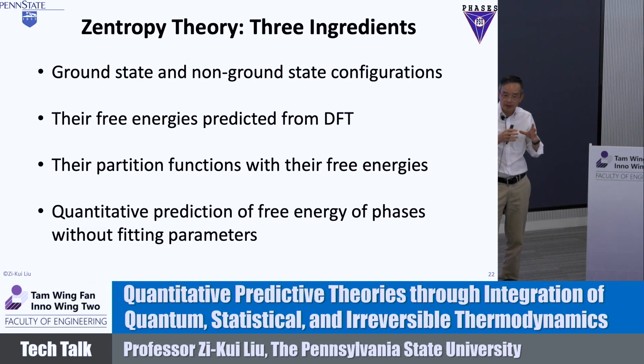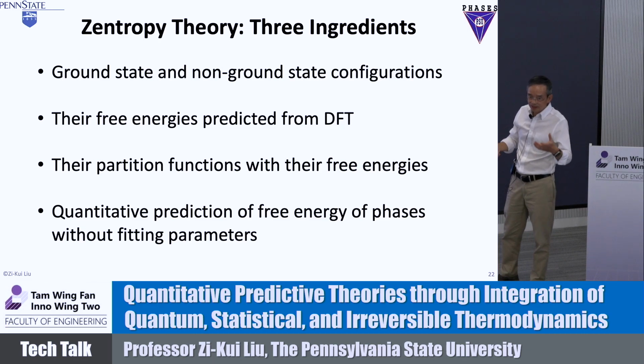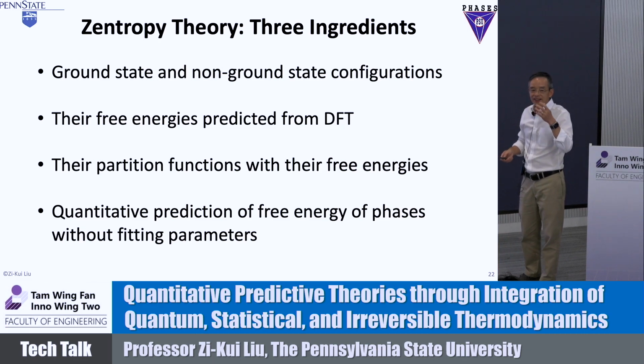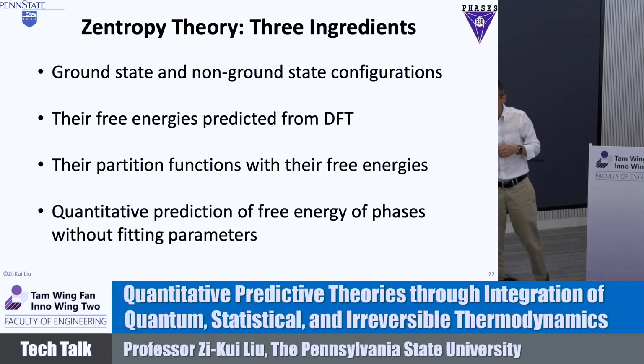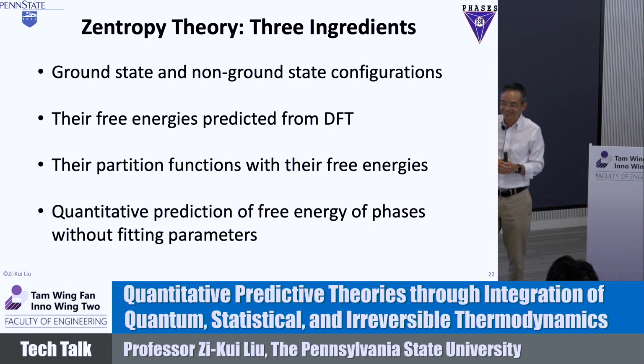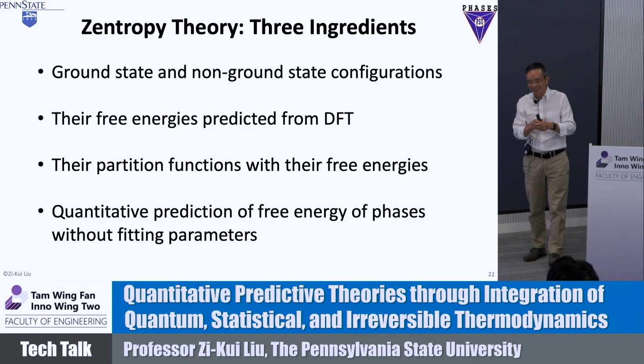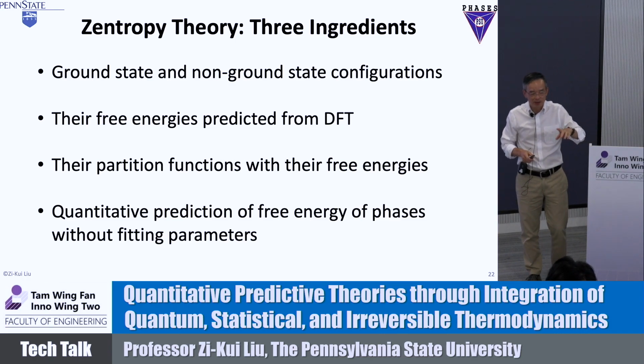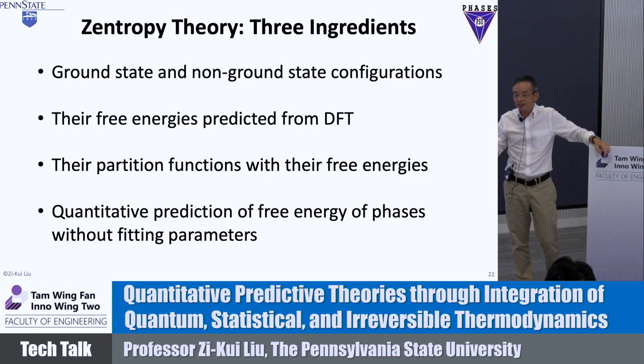Because MD has this fantastic approach, it can do a very large system efficiently. If you use the Zentropy, you cannot do so many of them, right? Because you're limited. Okay? Particularly if you have many configurations. Okay, and I hope really that'd be fantastic. I challenge Tongji to do one: the titanium PT diagram. Predict the titanium PT diagram with the experimental accuracy of temperature and pressure for all the phase boundaries. Okay, that'd be fantastic. I had one student do that one. We could not predict it, because at that time, our Zentropy was not developed yet. You could not do that, okay?